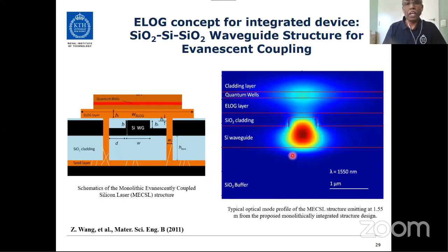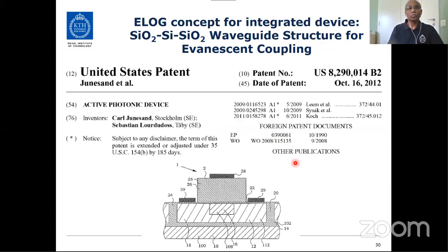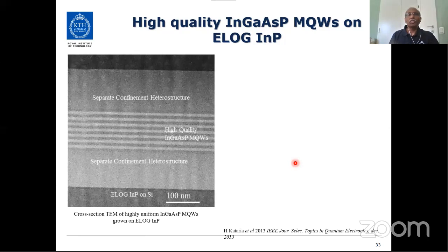And this is actually the simulation. So this has been demonstrated by bonding techniques, and not much has been done on the epitaxial side for integration. And actually we patented this concept. So I just want to show you some of the high quality material which we have grown. This is the high quality indium gallium arsenide phosphide multi-quantum well grown on ELOG indium phosphide on silicon.